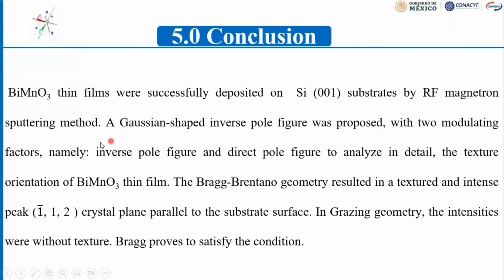We can conclude that the bismuth manganese oxide thin film was successfully deposited on silicon substrate by the radio frequency magnetron sputtering method, and a Gaussian-shaped inverse pole figure was proposed with two modulating factors, namely inverse pole figure and direct pole figure, to analyze in detail the texture orientation of the bismuth manganese oxide thin film. The Bragg-Brentano resulted in a textured and intense peak of the -112 crystal plane parallel to the substrate surface. In grazing geometry, without texture. So Bragg proved to satisfy this condition.